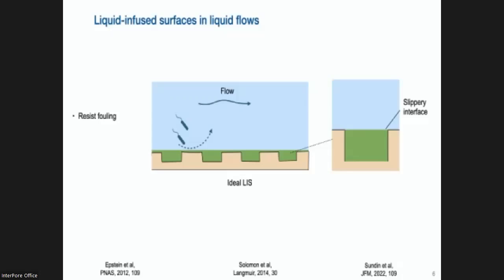In addition, when there is a flow, we have a finite velocity at the liquid-liquid interface, which gives us flow slippage, which means that we can use the surfaces for reducing friction or reducing drag. In addition, we can set in motion the lubricant and create a lubricant flow such that we can increase or modify mass and heat transfer of the surface. And we can show that you can increase the heat transfer by 20% by tuning the thermal conductivity of the lubricant with respect to the solid.